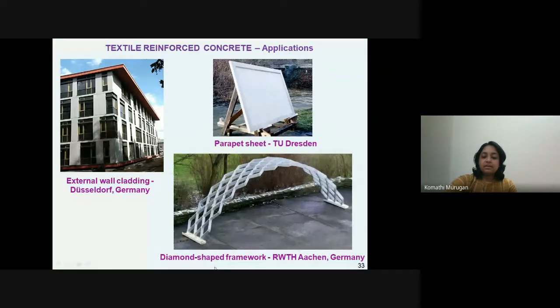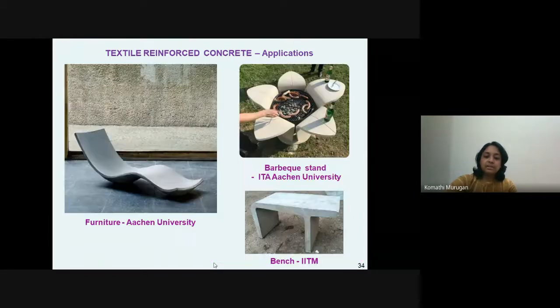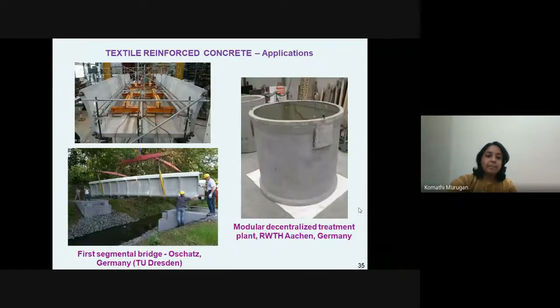And this image shows a diamond-shaped architectural framework, which was developed by RWTH again. And some interesting furniture, barbecue stands, said to certainly work well in the presence of the hot coal that is present inside. And we at IIT Madras also developed certain benches of sectional thickness around 60 to 80 mm. We have put these benches to use around our laboratory. It's been 4 to 5 years since we prepared them, and they were found to work really well with all of the sitting and standing loads on them.